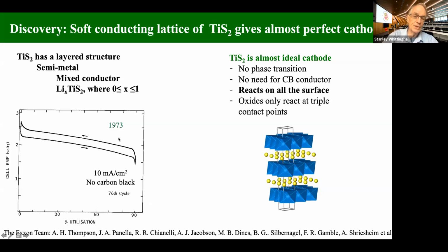On recharge, you can see the curve follows exactly the discharge one. The difference here is just the resistance loss in the electrolyte. And I should emphasize this was run at 10 milliamps per square centimeter, much higher than any lithium-ion battery is today, and that's partly because of its metallic conductivity. So another advantage of it being a metallic conductor, the reaction can occur at all points where the material touches the electrolyte, not just where material, carbon black and the electrolyte are in contact, so we get much higher reaction.